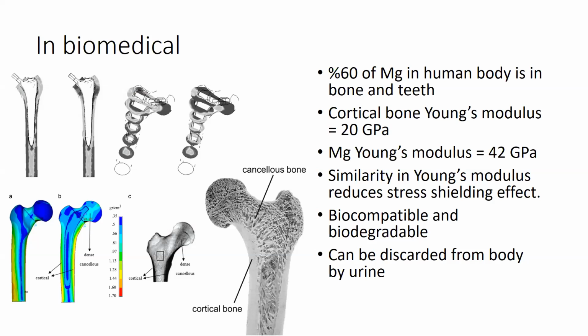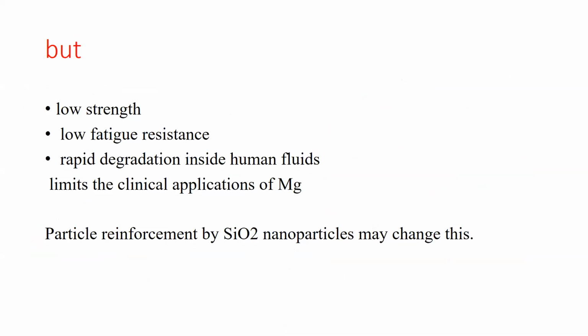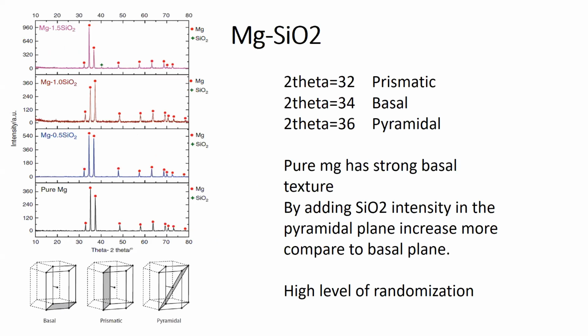Normally, temporary implants should be removed from the body after about 1.5 years. But low strength, low fatigue resistance, and rapid degradation inside human fluids limit the clinical applications of magnesium. Particle reinforcement by silicon dioxide may change this. As we can see, adding silicon dioxide at 0.5, 1 and 1.5% volume changes the texture.